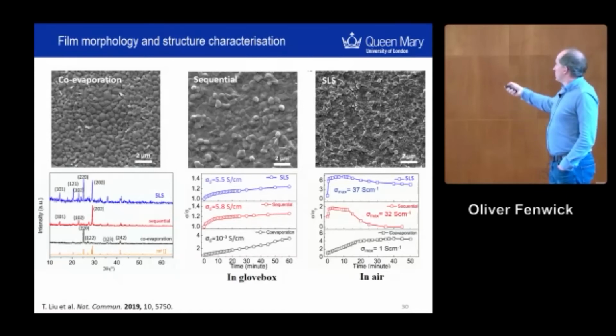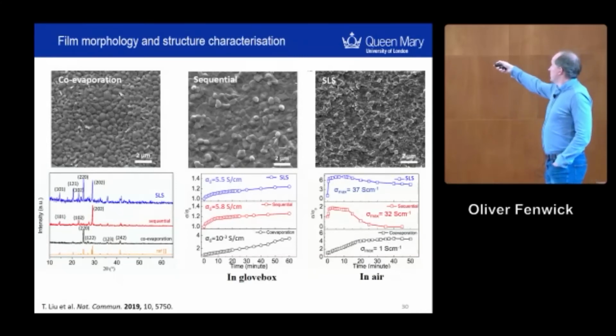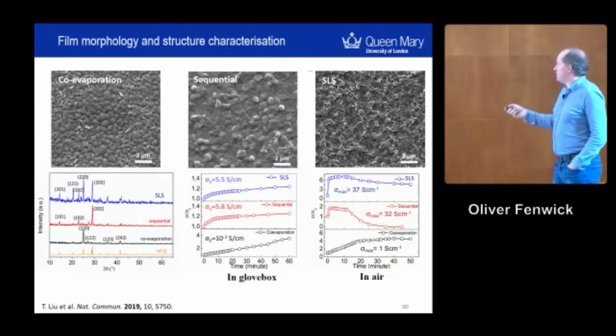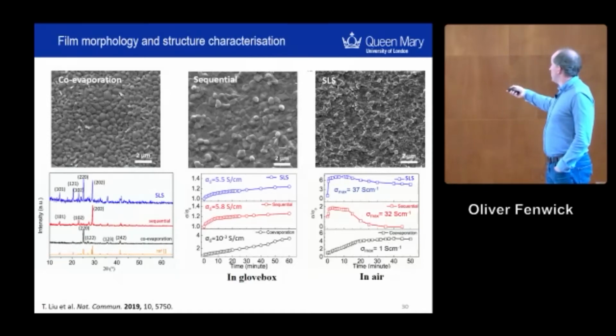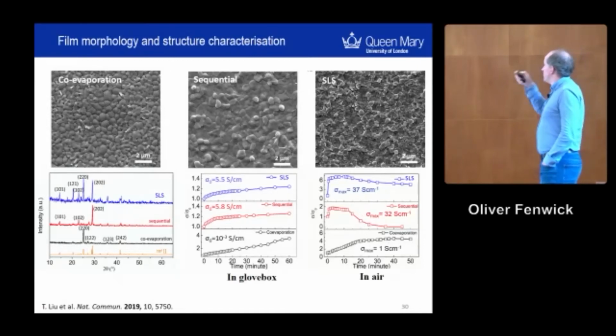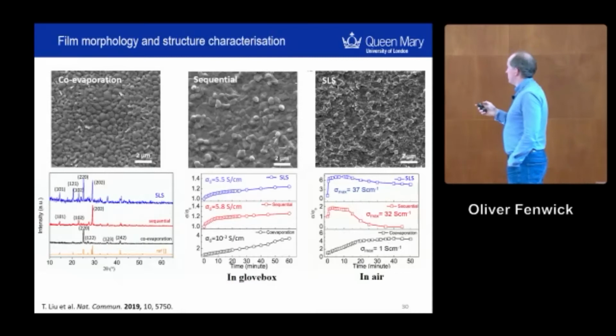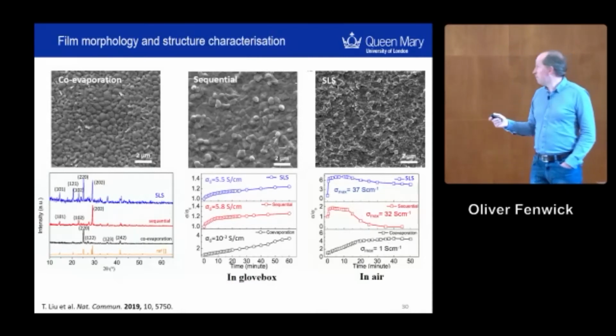So if you leave these in air for a long time, you see the electrical conductivity increasing. In the case of the co-evaporated film, that happens, as for a perovskite, very slowly. It's over the period of an hour that it reaches a peak. In the other 2 cases, it goes up very sharply and then starts degrading after that point. On the other hand, the maximum electrical conductivity reached is much higher, 30 or so Siemens per centimeter in this case, and it can be higher.